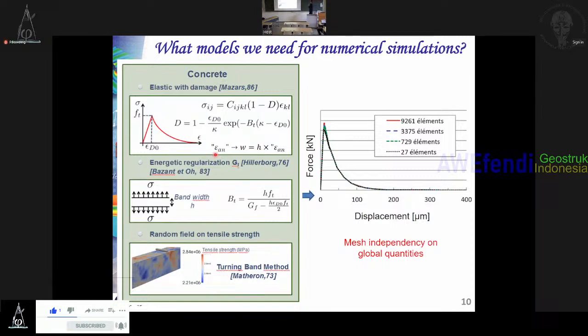So it's not the real crack opening, but you can calculate the anelastic strain. Normally it should have been removed. If you are at this point, after the linear elastic behavior and after the damage evolution, the softening, if you calculate this strain, you know the elastic strain. The difference is what we call the anelastic strain.